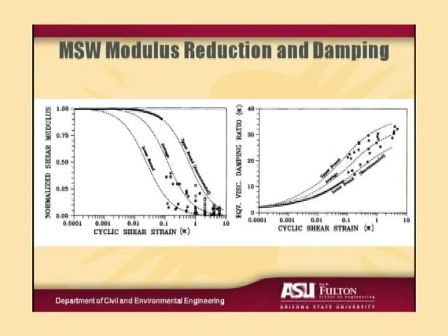And from our laboratory tests, we developed a family of curves to represent modulus reduction and damping: upper bound, average, and lower bound. But based on the back analysis, our best estimate was the upper bound modulus reduction and lower bound damping curve. And those two are compatible. The upper bound modulus goes with the lower bound damping. So we looked at that full range of curves in our analysis, but our best estimates were based on the upper bound modulus and the lower bound damping curves.